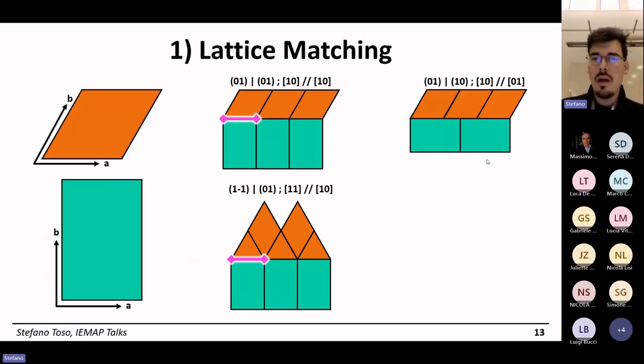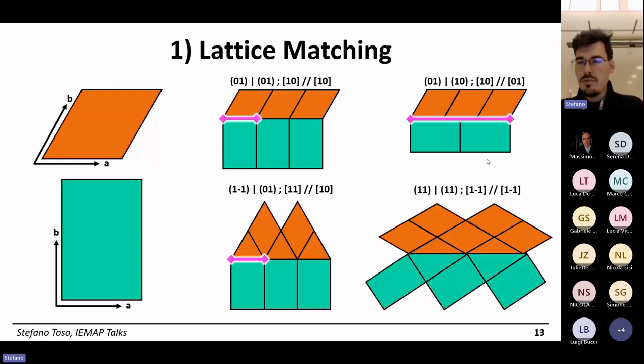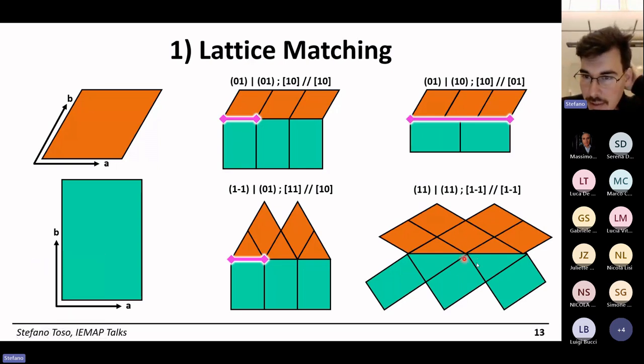Then you have this one where you tilted the cyan material by 90 degrees, and you do change the periodicity at the interface. And then you have this one that is a bit more messy. In fact, if you carefully look at the corners here, you don't have a great match. This is the strain that we were talking about. You still have a periodicity, but it is strained, right?